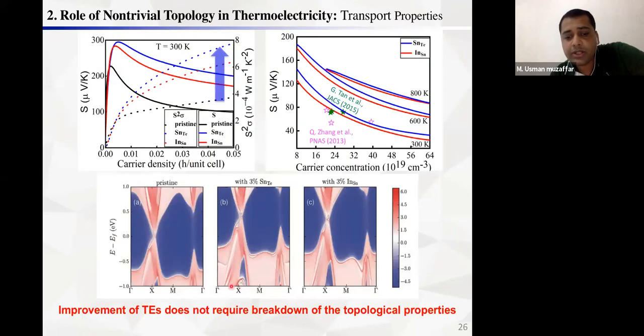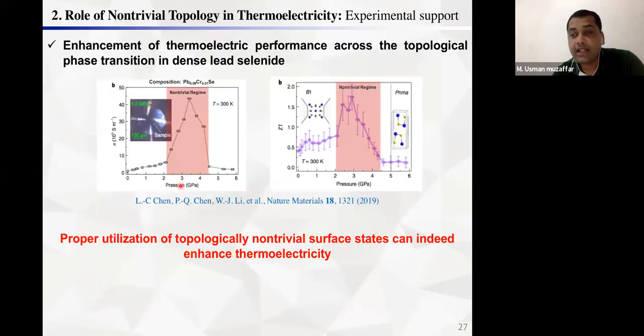So here we can conclude that the improvement of thermoelectrics does not require the breakdown of the topological properties. Here is the experimental verification of our conclusion, which appeared in Nature Materials. They considered a PbSe system. This PbSe has a very similar crystal structure to the SnTe system, but it is an intrinsically topologically trivial case. With increasing pressure, they found that up to 2 gigapascal the conductivity does not increase significantly, but beyond this it is significantly enhanced. After reaching the peak at 3.5 gigapascal, it significantly decreases.